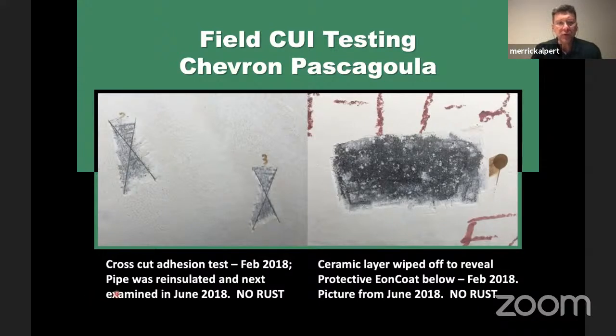And so if you just look in Chevron's own words, what they do is they spray the coating, they let it cure, they then scrape it off, they then bring the pipe up to temperature and run it for months and months and months. They then take the insulation blanket off and take these photographs. So look at what's happened. Even in a CUI environment, in those brutal conditions, even if you scrape away the outer layer of the coating, the passivation layer still prevents corrosion. Or in Chevron's words, just as written, no rust.